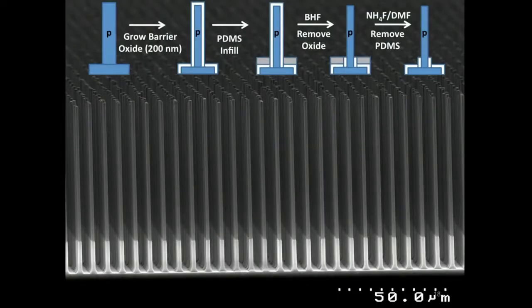Because then if a photon goes down the middle and hits a cheap scatterer, it gets bounced sideways, and once it gets bounced sideways, it gets absorbed by a rod and then multiply internally reflected and trapped in those optical concentrators, never to escape. And in fact, by using cheap scatterers and controlling where we put them, we can get the absorption properties integrated over time of day better in these systems than the best commercial anti-reflection coated silicon crystal solar cell with no anti-reflection coating whatsoever, by just using simple photon management principles of cheap scatterers filling the volume in between the rods.